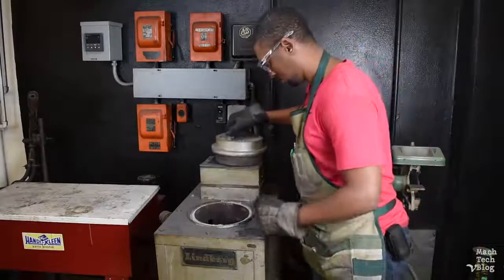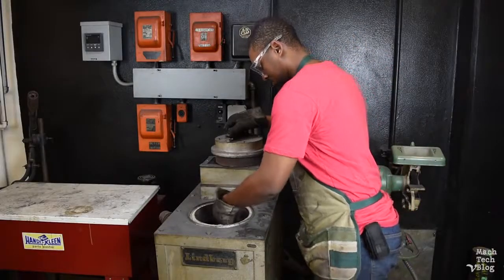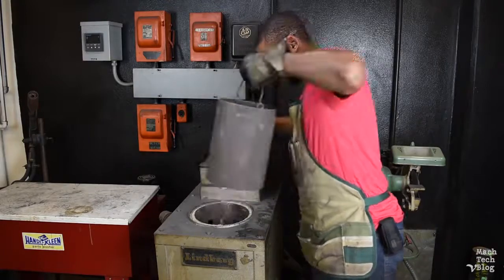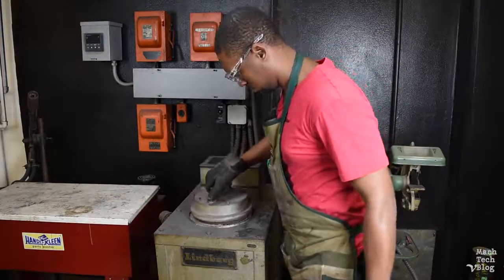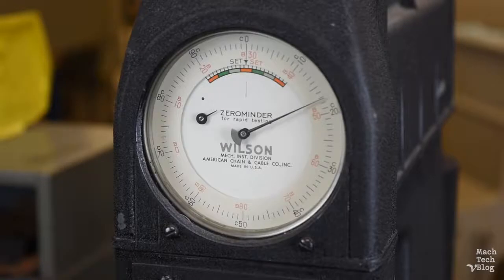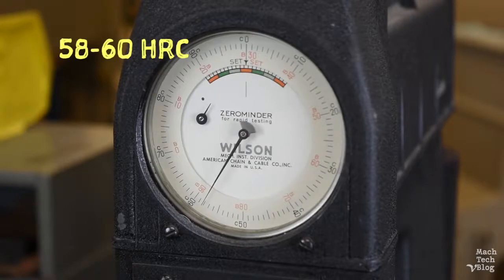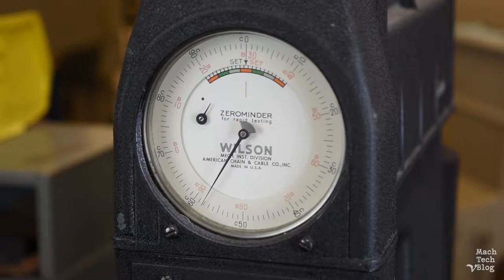Remove the parts and let them air cool at room temperature. Don't go dunking them in water at this point. It's normal to lose a little bit of hardness during the tempering process, but these parts are ready to be finished machined on the surface grinder.